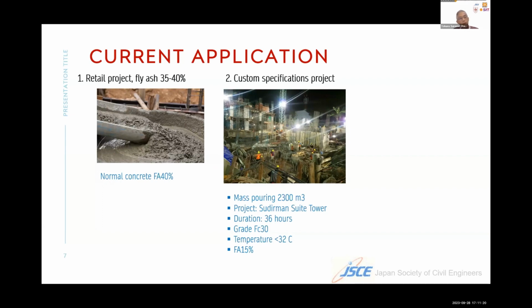So in the concrete, we use fly ash of about 15%, and to minimize the temperature, we use ice. So the temperature is still under control, less than 32 degrees Celsius.